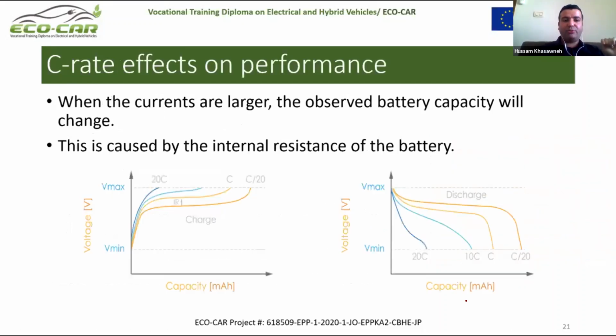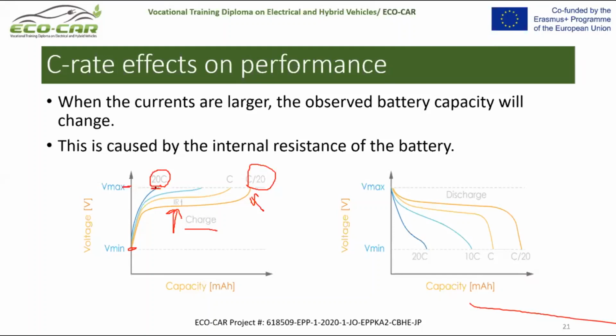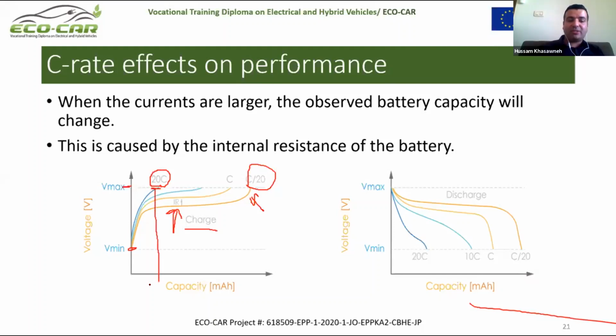The effect of the C rate on performance is, as we said, when the currents are large, the battery capacity will change. If we look at this curve, it's a very, very slow charging. We start with V minimum and we reach V maximum through this very comfortable curve. This curve is very close to the ideal characteristics, and that's very good. However, if we go to a faster rate, like 20C, this is a very, very fast charge. We can see that we reached here very fast. We are not using the complete amount of the capacity. We are just using this amount of the capacity. So it's very important to understand this.